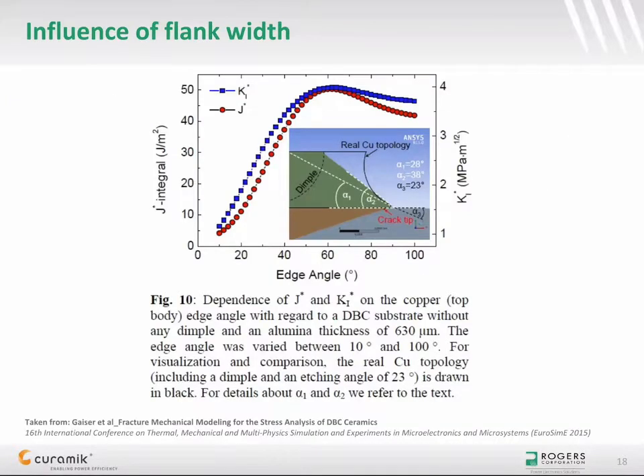In this finite element modeling, the edge angle was varied between 10 and 100 degrees for a DBC substrate without any dimple. From 10 to 62 degrees, stress is increasing, and from 62 degrees, a slight decrease can be seen before the values converge. The increase is again due to the fact that the more copper exists, the higher the compressive forces upon the ceramic parallel to the copper-ceramic interface will be. This means that the most important property preventing the DBC ceramic from the failure of conchoidal cracking is that the etching angle of the copper end tail is as small as possible. The most important method to prevent the ceramic from cracking in the vicinity of the copper tail is to decrease the stress intensity by a small copper tail etching angle. This may be even more efficient than dimples and should not consume as much area as dimples.